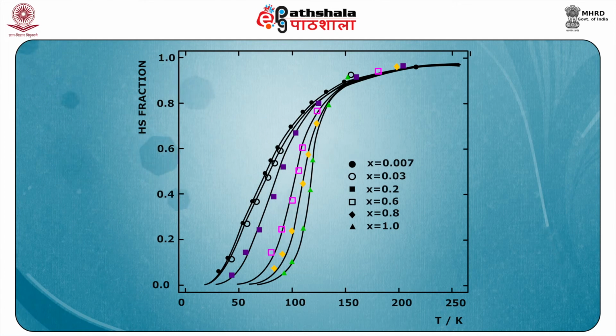This was shown first for the mixed crystal series of Fe(2+)x Zn(1-x) 2-picolylamine 3 chloride dot ethanol with x ranging from 0.007 to 1.